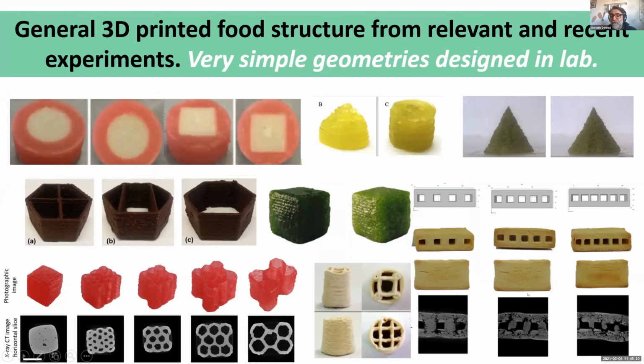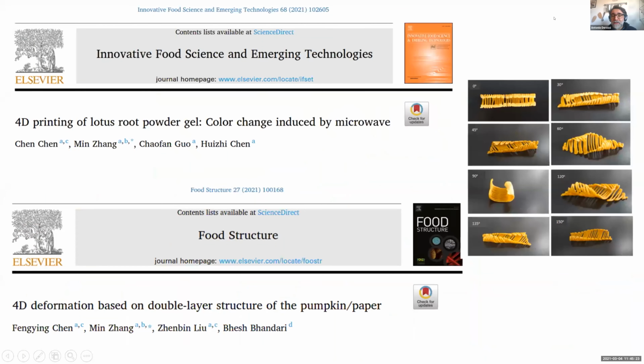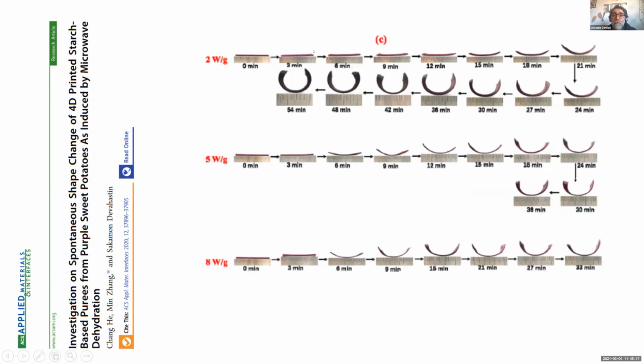And these are good examples of 4D printing, because in the last 2 or 3 years, some researchers, particularly Min Zhang in China and Bhesh Bhandari in Australia, started to think, okay, it is possible to modify some property over time, for instance, the shape in these 2 papers, or also the shape activated during microwave heating. Really interesting in this case is to see that after 3, 6, 9, or 24 minutes of microwave heating, we can obtain a different shape. We can improve the shape and change the shape of our structure.